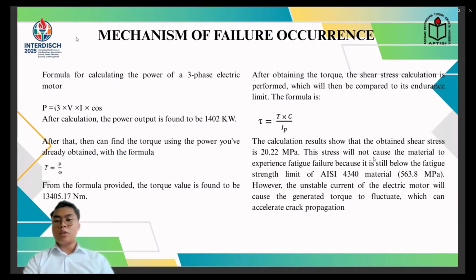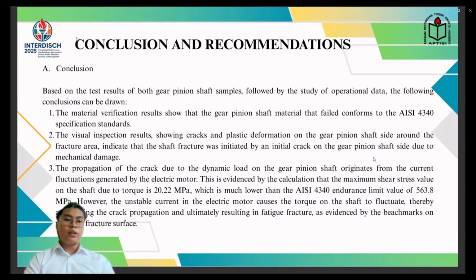This stress will not cause the material to experience fatigue failure because it still falls within the fatigue strength limit of AISI 4340 material. However, the unstable current of the electric motor will cause the generated torque to fluctuate, which can accelerate crack propagation. And this is the conclusion.